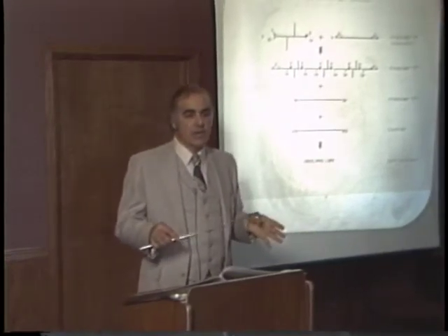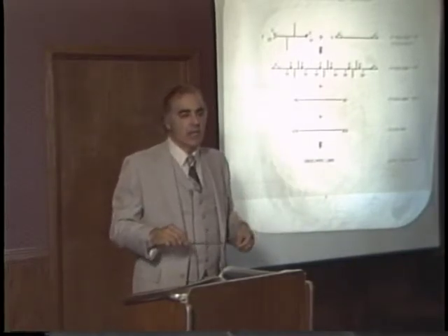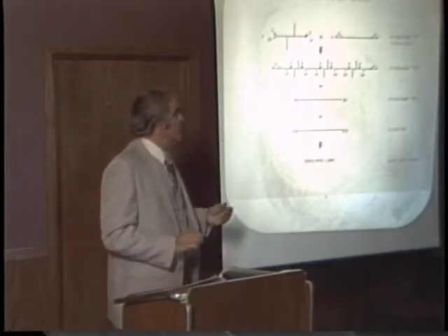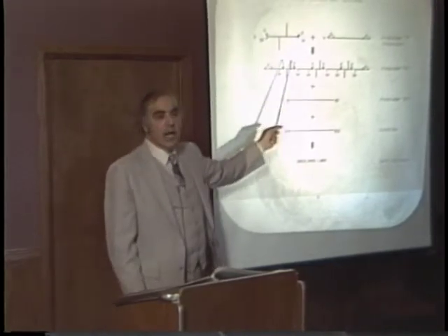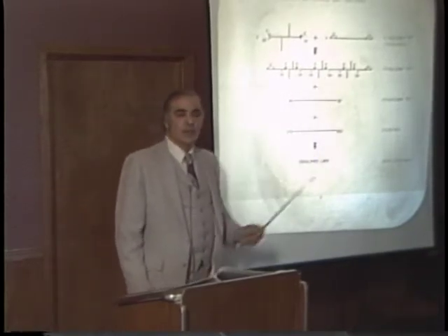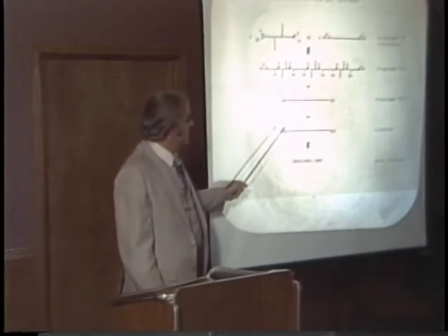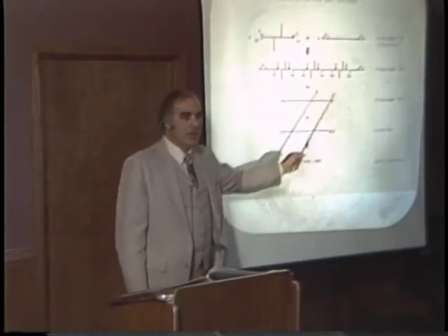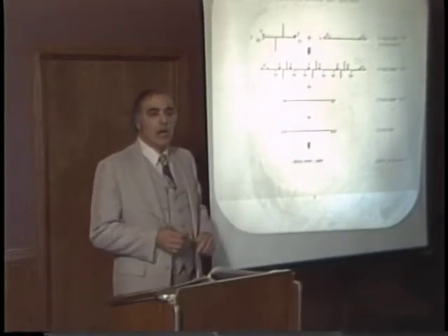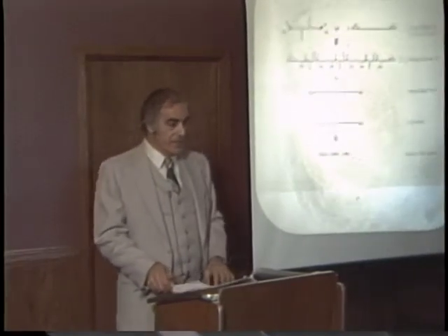Normally, if you have a tightly cross-linked matrix with no groups sticking out available to interact with the prepolymer of the propellant, you can't get good bonding. So with this system, we're able to go to high cross-link densities and still get good bonding. So we chose to make the prepolymer with that. Now, as I said, that has a high glass transition temperature. By combining in another material, grafting it in this fashion, we come up with a fairly highly cross-linked liner that has some rather unusual properties. Next slide, please.